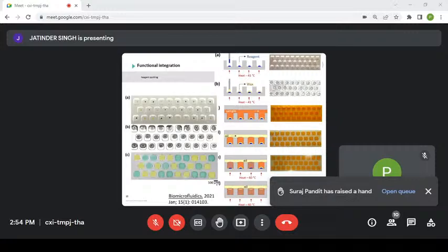And this is the way it looks like. You can see that there were alternating bits of green and blue and yellow. So yellow and green dye being deposited, immobilized in the wax, then the water was put on top, and you can see here the reservoirs contained the corresponding dye solution. When water was added, oil on top, you heat, you melt the paraffin, and then you get reagents back reconstituted in solution and ready to use.